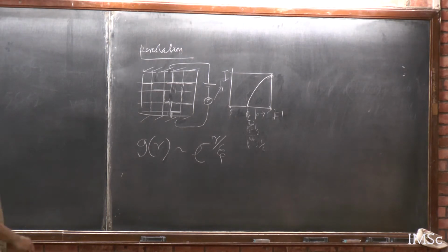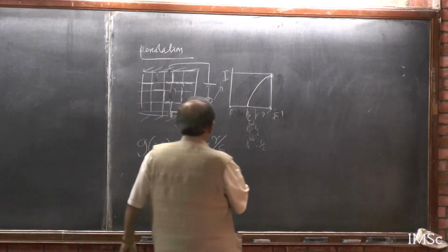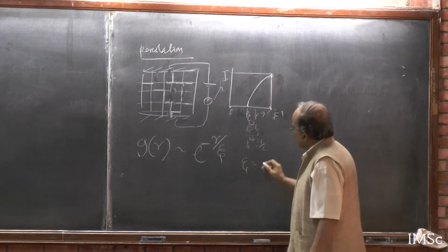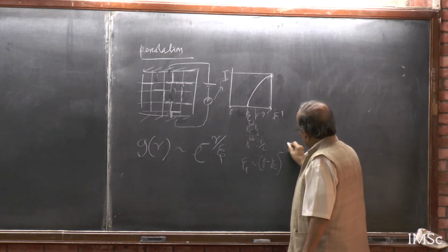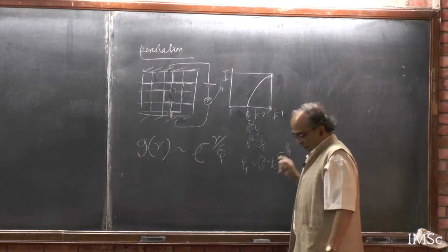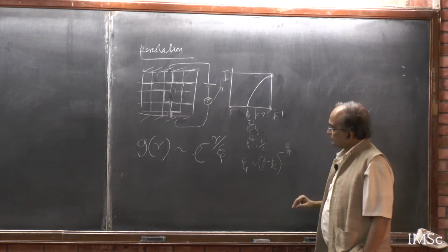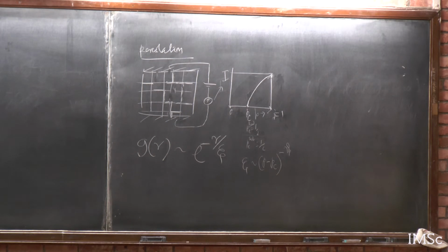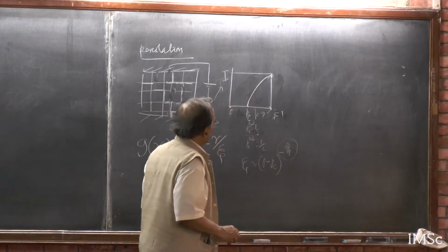If we had time, I would find out what this is. It says we can argue why this happens: it is (P minus Pc) to the power minus nu, percolation. It's called the correlation length exponent. It actually diverges as you approach the percolation threshold. This is established in various ways, and as I said, this is the correlation length exponent, which is quite an interesting and important one, and similar things you can